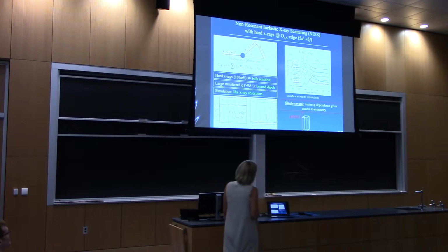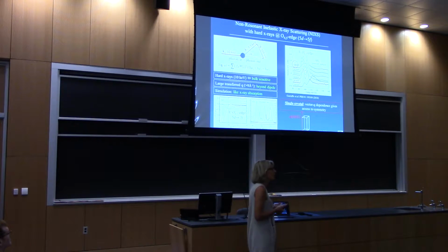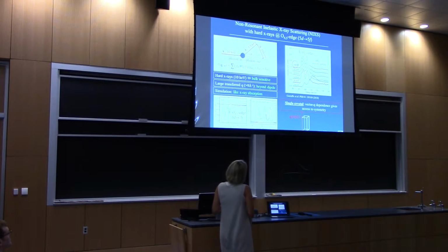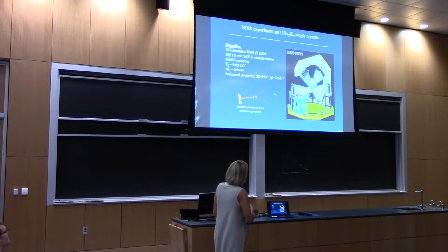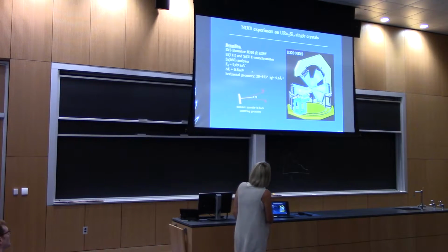And when we do such an experiment now on a single crystal, with the vector Q parallel, let's say, to c, and in the plane parallel to 100, then we can do the same as in an X-ray absorption experiment with linearly polarized light. This is just showing you the beamline where we did it, ID20 at ESRF. We come in here with photons, we scatter, we do backscattering to have high momentum transfers, and this is our final energy, 9.7 keV, our resolution, and these are the momentum transfers we are working with.